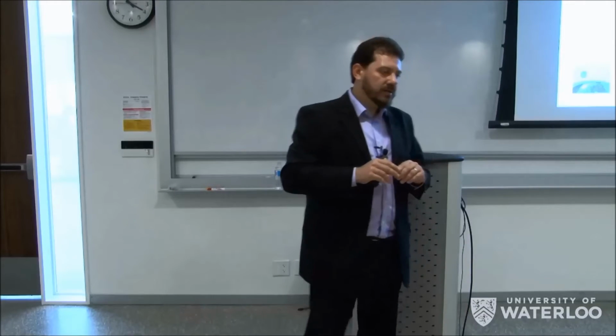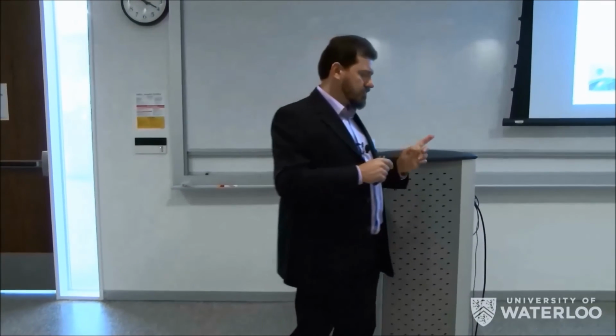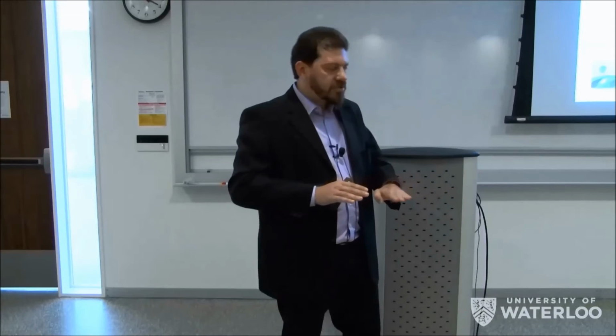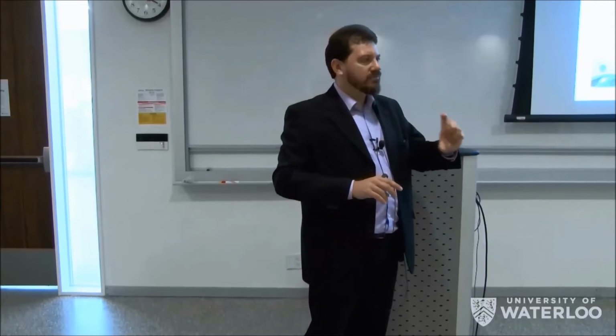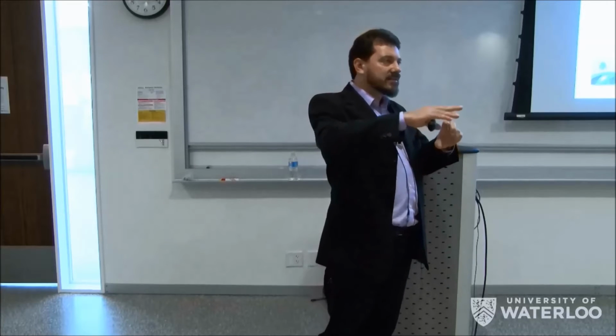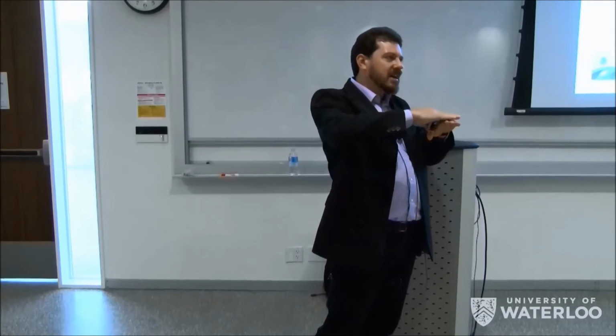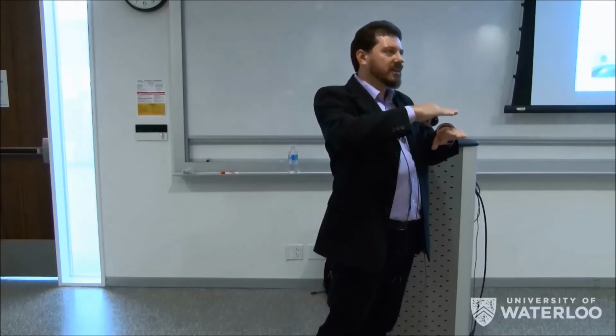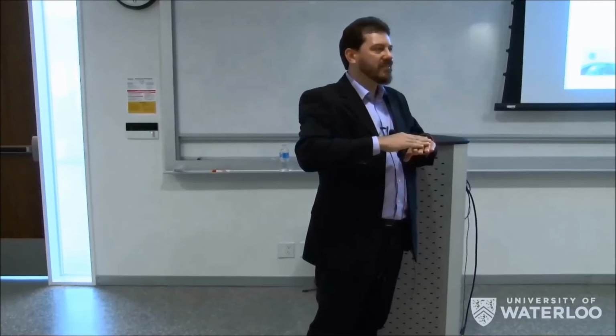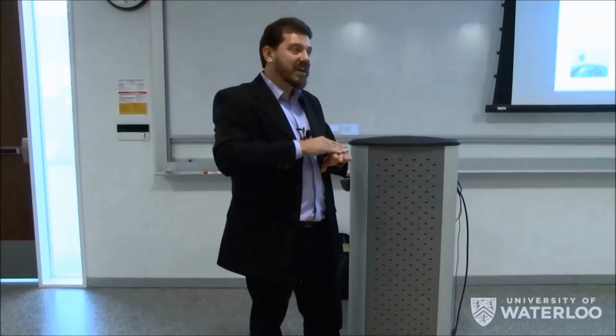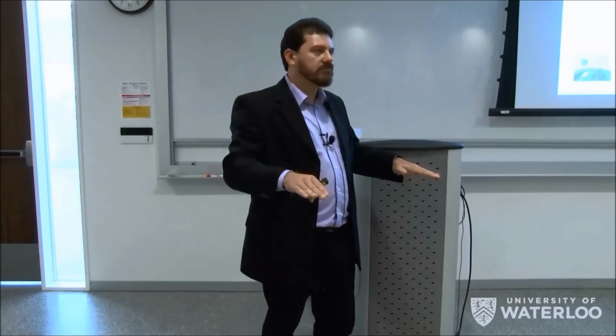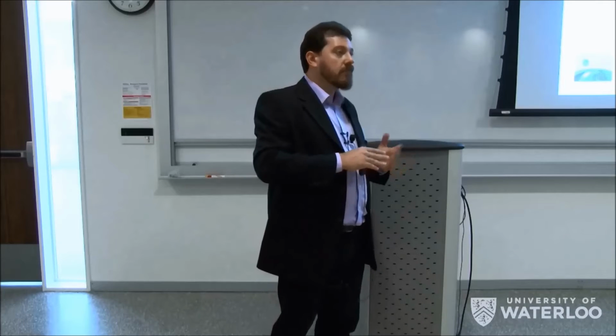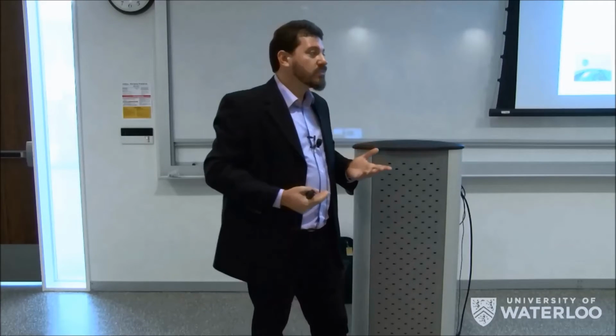We did it at different levels. We have an experiment I didn't show here where we changed the height of this finger to the point that the tube just touches slightly or loses the contact. We didn't see any difference from those devices. The pressure didn't make any difference. To some extent, in some cases it does, because the roughness smashes the tube and I have a short circuit. But this was one question that passed me.